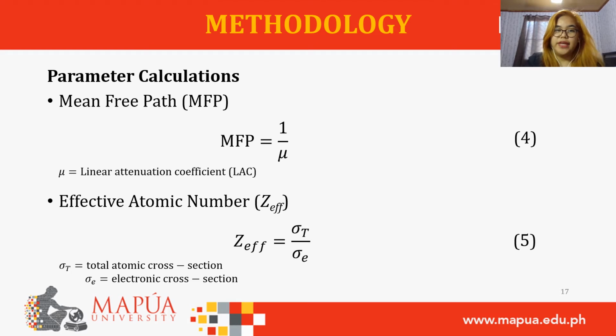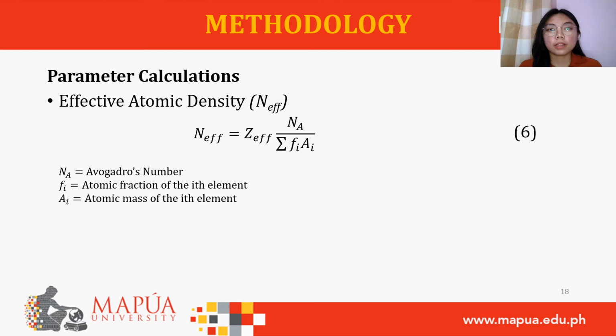Similarly, the MFP can be calculated from the inverse value of the mu. On the other hand, the Zeff can be calculated by dividing the total atomic cross-section by the electronic cross-section. The effective atomic density can be obtained by multiplying the effective atomic number by the ratio of Avogadro's number to the summation of the atomic fraction times the atomic mass of an element.